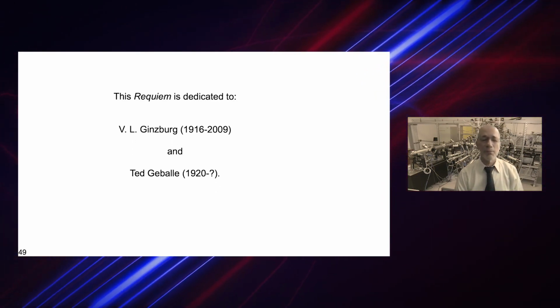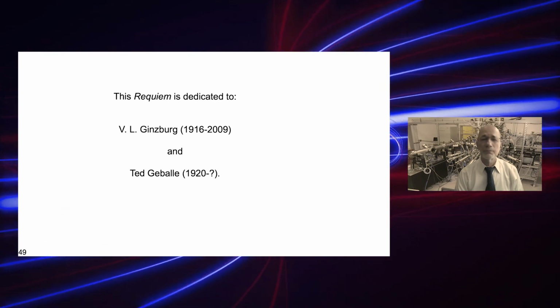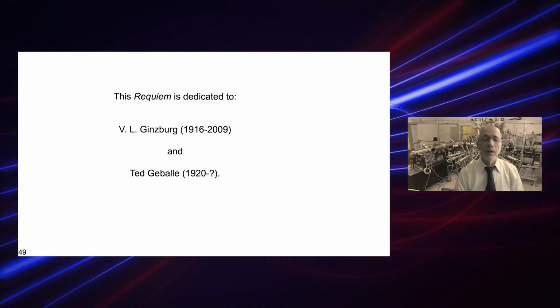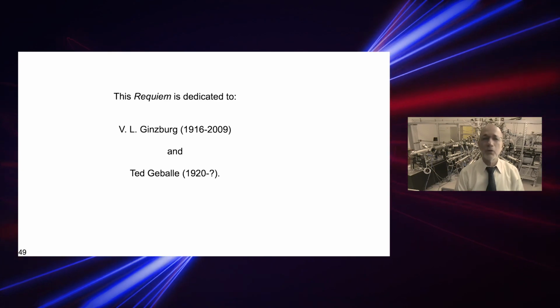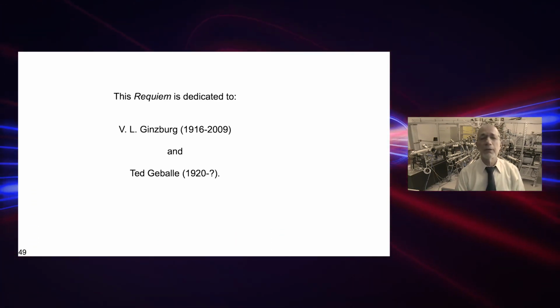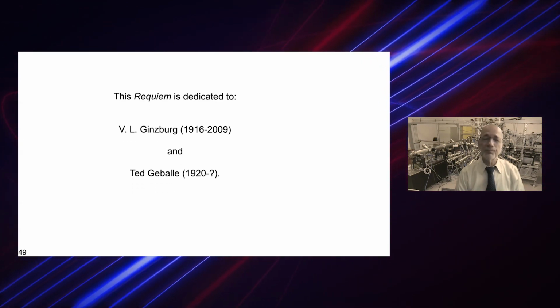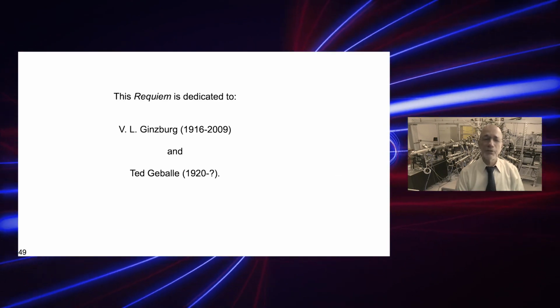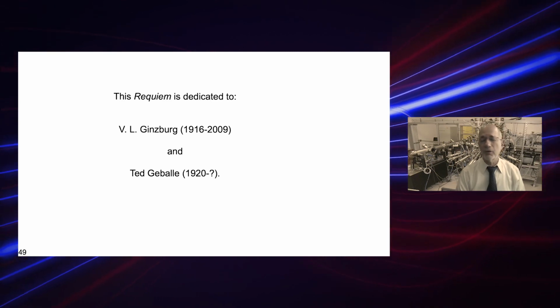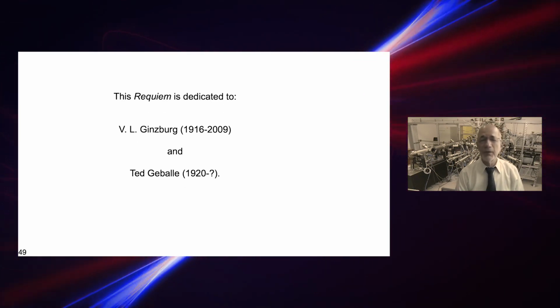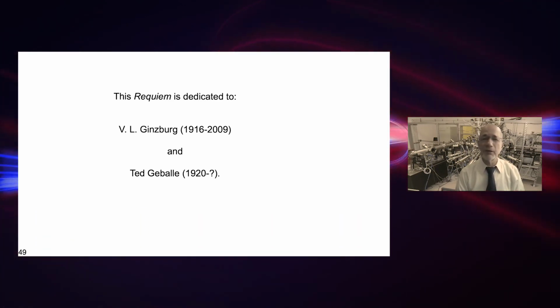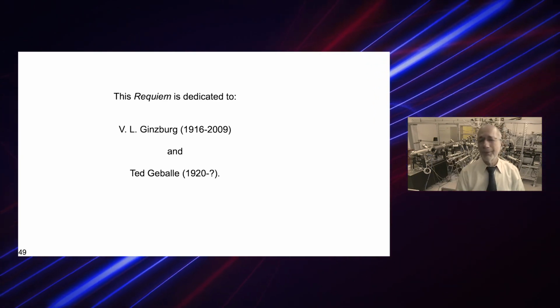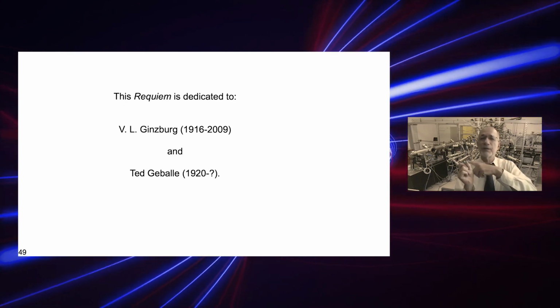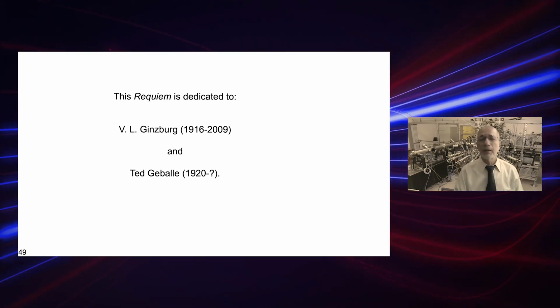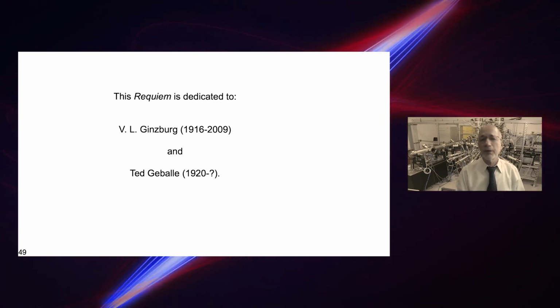Another question is about magnetoresistance: how does the behavior depend on the direction of the magnetic field? The resistivity is linear in field. The field dependence has not been studied very much. There is one report which comes from Nigel Hussey's group, and then we have our own unpublished data, but I'm afraid only on one doping level. Both of these showed that there was no difference whether the field was parallel or perpendicular, and that seems to rule out the orbital origin. It looks like it comes from spin.